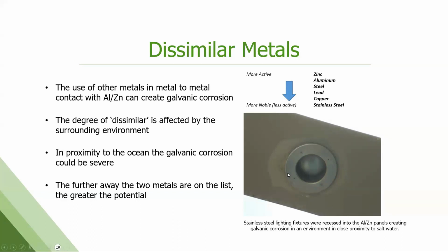So this is a stainless steel lighting fixture canister recessed through a galvalume painted panel that is 300 feet off the surf break in San Diego. So high salt content, highly corrosive. This kind of lighter area, this rim that you see around there, that is the paint bubbling off because the substrate underneath is being destroyed and it has nothing left to stick to. Dissimilar metal corrosion. Not good. We have whole books of technical bulletins and papers on this topic if anyone wants to know more.